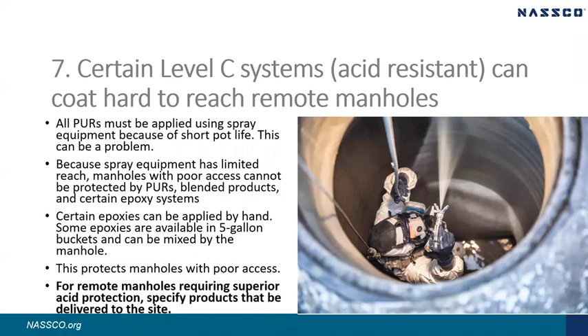Point 7, certain level C systems can coat the most remote manholes while others struggle to do so. Because of short pot life, all polyurethanes and polyureas and some epoxies must be applied using spray equipment, which can have limited reach. Certain epoxies can be mixed and applied by hand. When specifying acid protection for manholes with remote access, it is useful to consider the limitations of the delivery systems and specify products that can be delivered to the site.